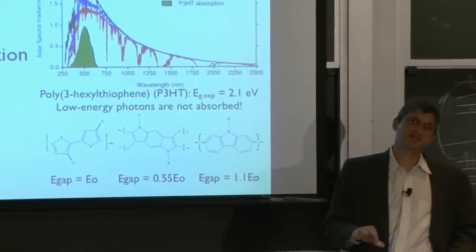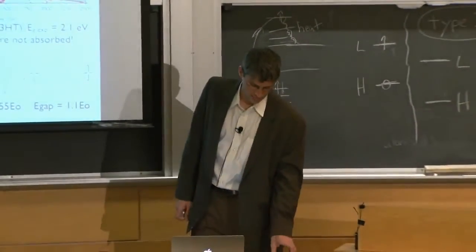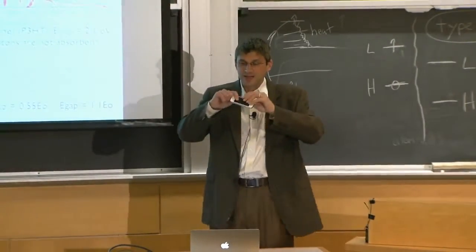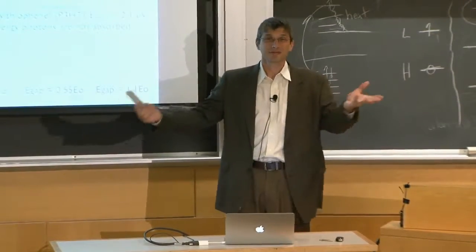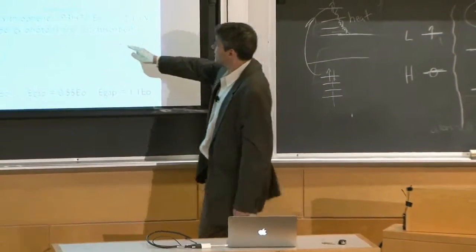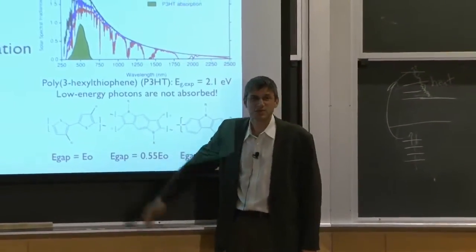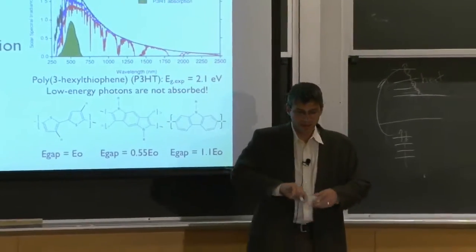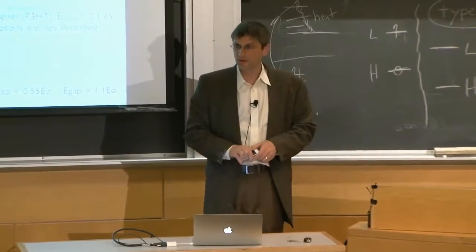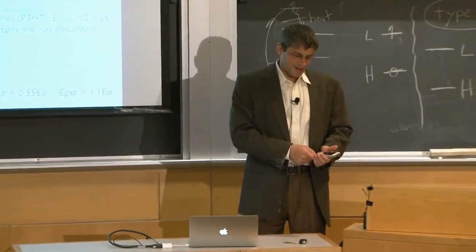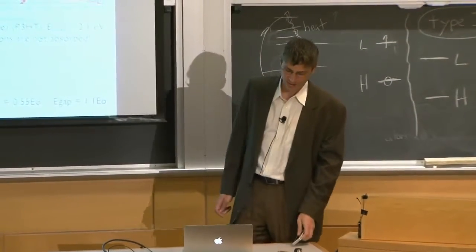Now the problem is efficiencies are very low still, right? One of their products is like this size, and it's all packed in, and you can unfold it to the size of this table because it's just flexible and thin, and you put it on plastic instead of glass, right? P3HT is a plastic. It's a cheap solution processable plastic, and the films only need to be 100 nanometers thick. So you can put it on this flexible thing that folds up into a wallet, and you unfold it, and it's the size of the table, and you plug it into your cell phone. And you wait the whole day, and you get like 2 minutes of talk time. They're very low efficiency, okay?